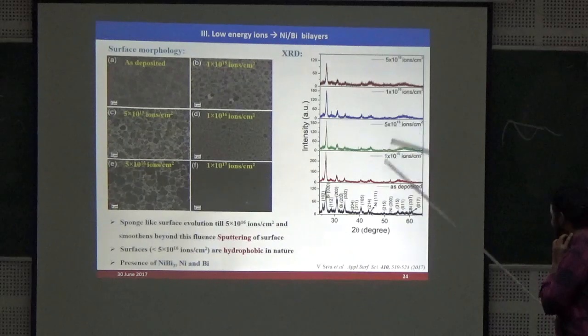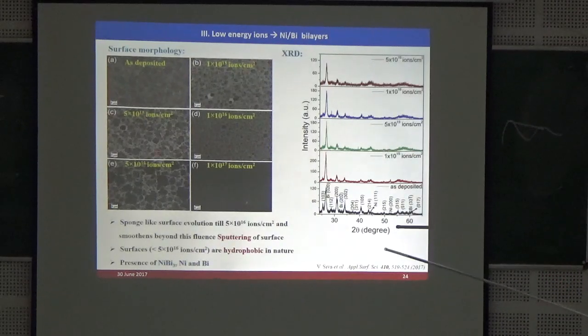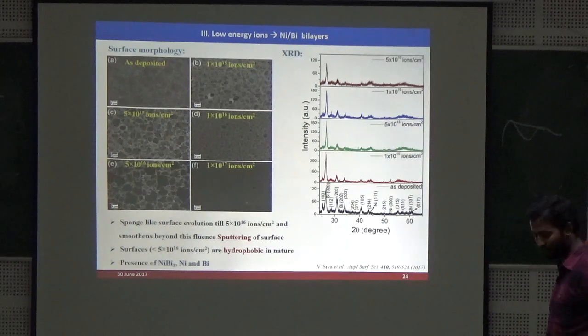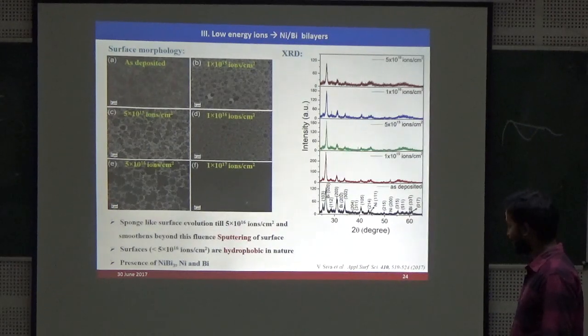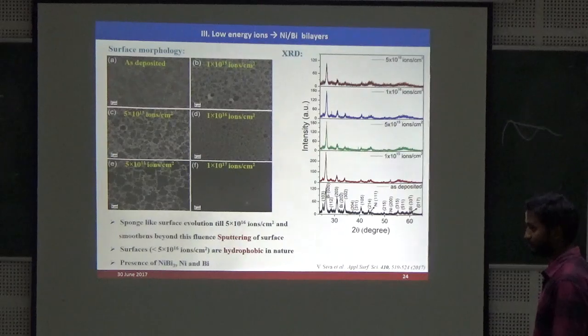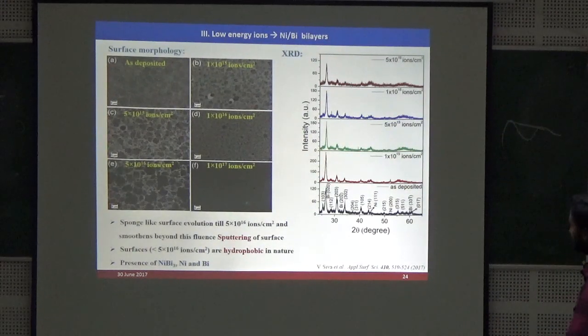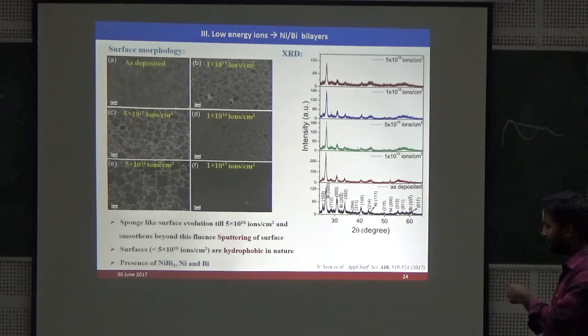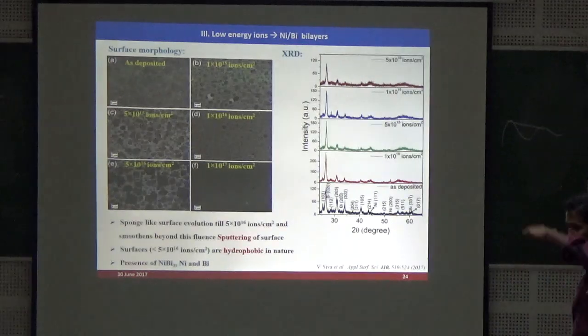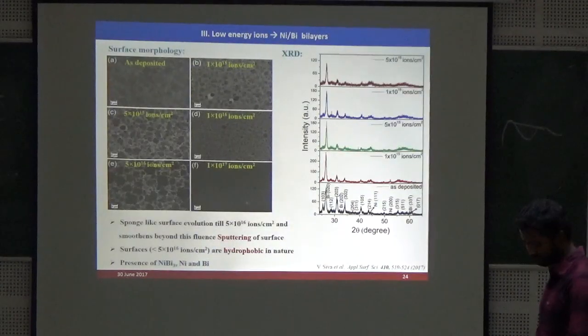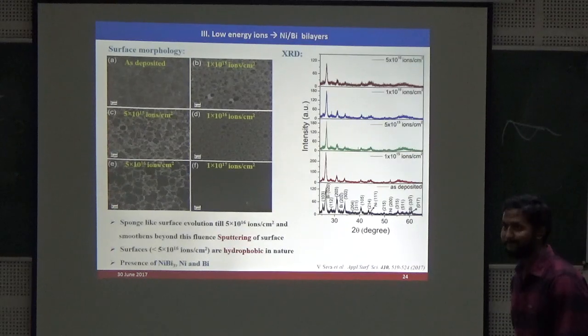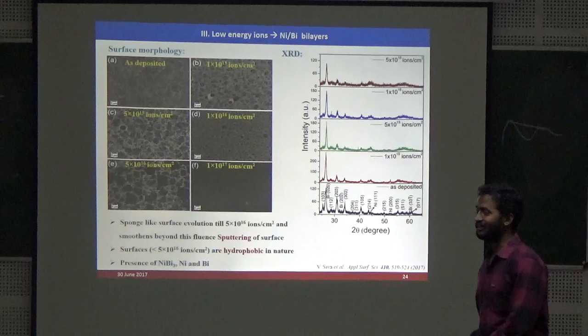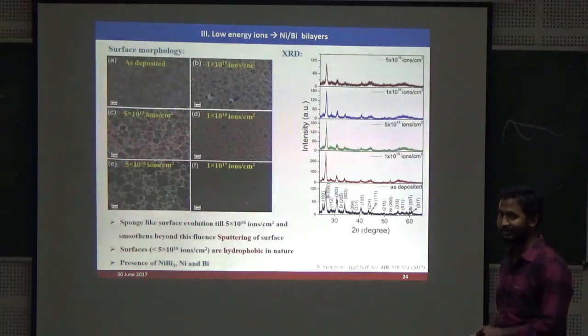So XRD measurement suggests that in all the cases we have nickel bismuth along with NiBi3 formation. So in this case, there is no structural change. Sputtering is there, but it is so much that it will remove almost all the bismuth top layer. In this case, it is low energy, so ions will have sufficient time to interact with the surface atoms, so they will eject the surface atoms, which is nothing but sputtering. Is the surface hydrophobic or hydrophilic? So we have to measure the contact angle. The angle is more than 90 degrees.